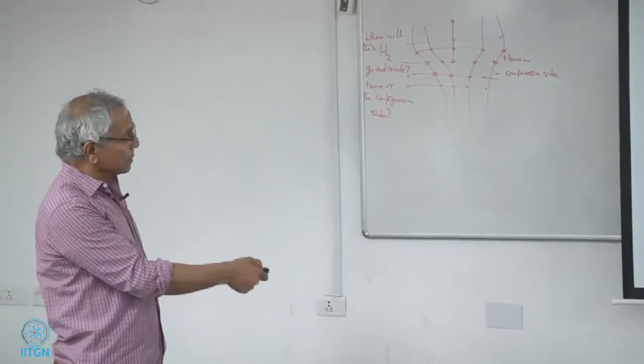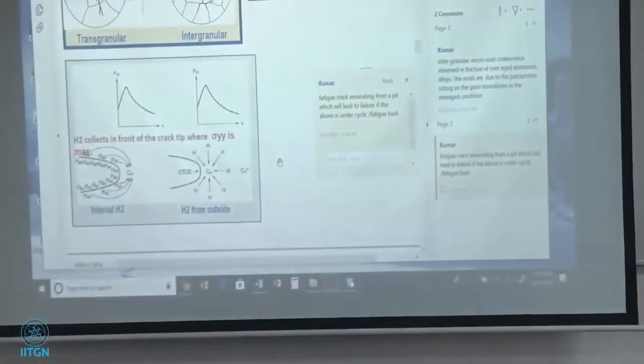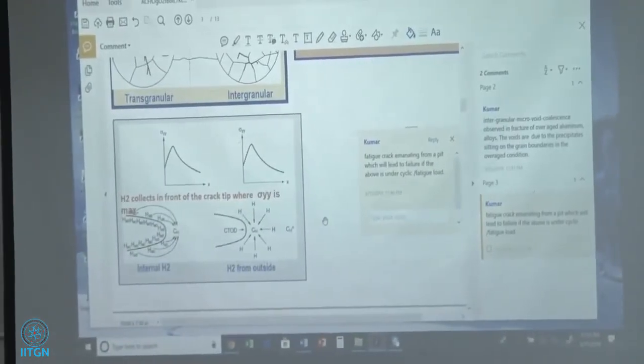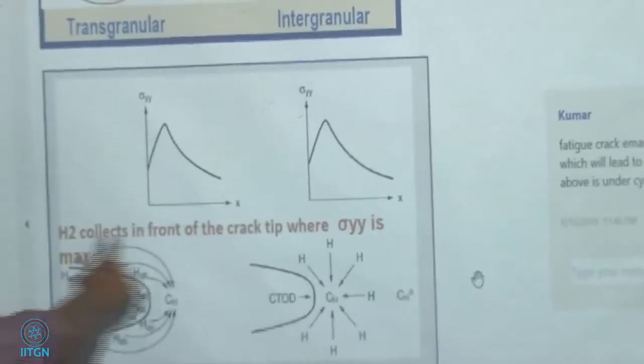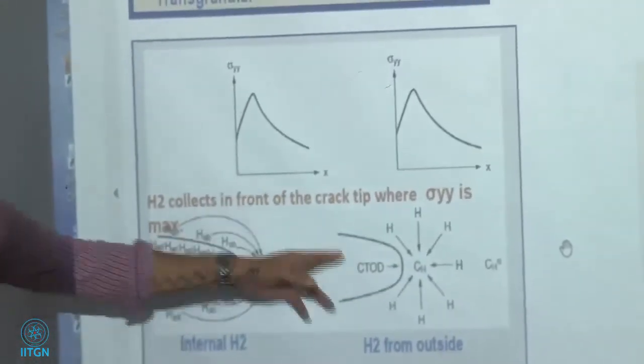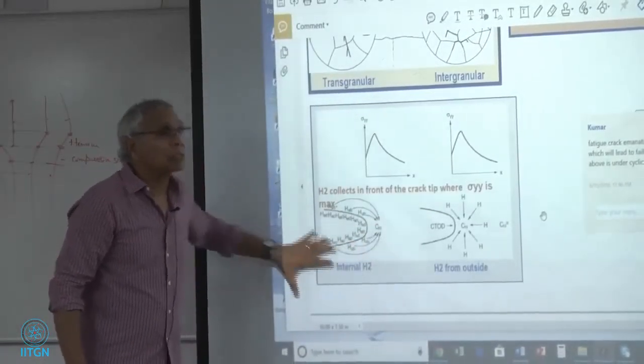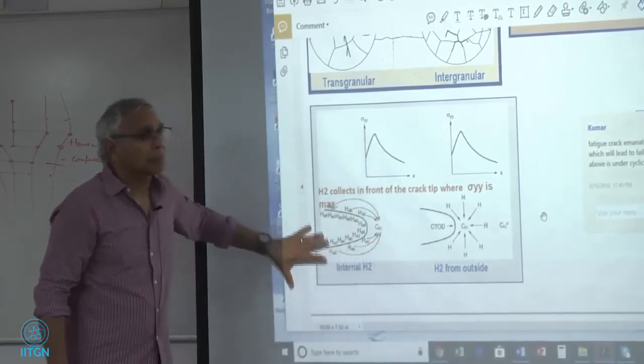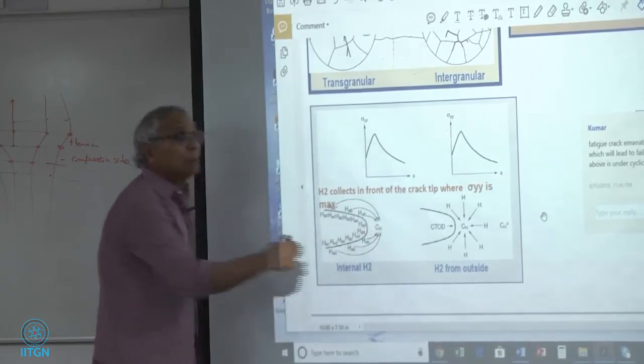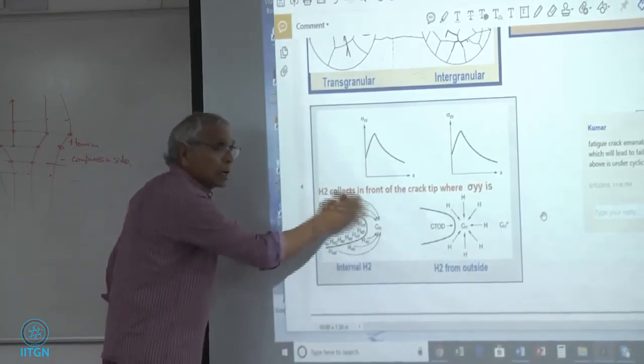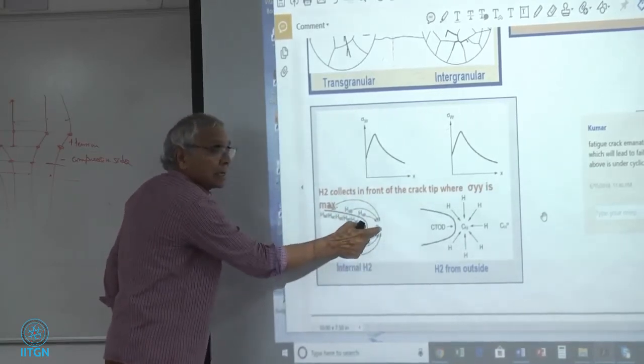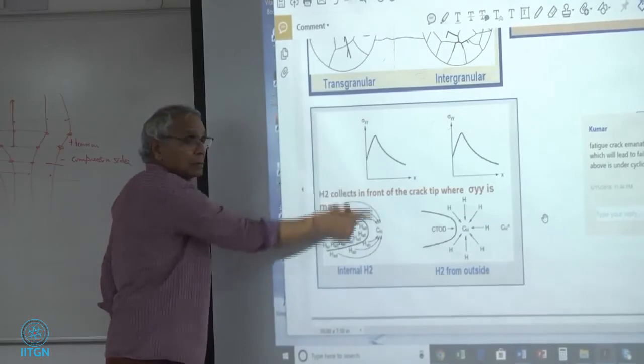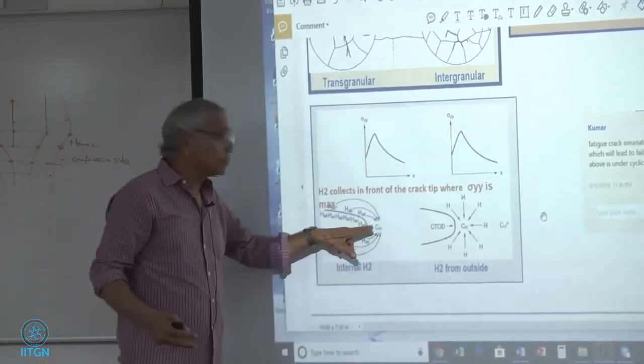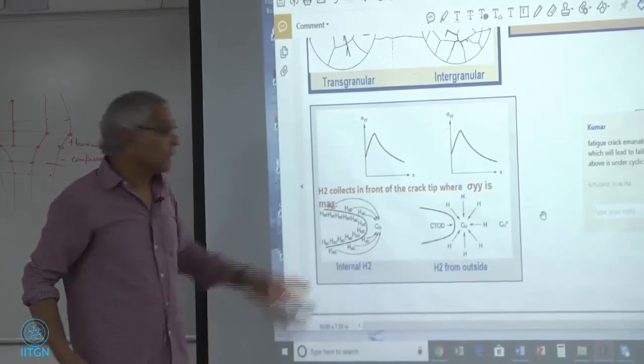Okay. So here we are. There's the maximum stress in front of the crack tip. Okay? Maximum stress. So whether it is internal hydrogen, yesterday we were talking, Bhanumati, remember? If I have a sample here, and my sample has 100 parts per million of hydrogen macroscopically, right in front of the crack tip it will be much, much more than 100, because the hydrogen will all come from everywhere and sit at the highest stress level. So even though it's 100, here it may be 300, 500, and I can have hydrogen embrittlement.